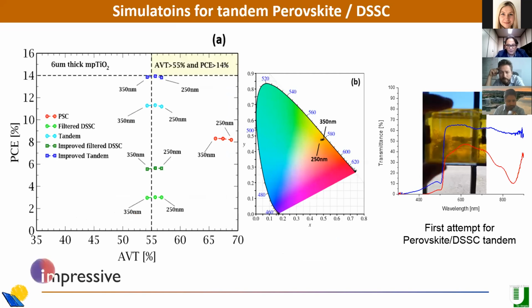At the moment, we have just the first attempt for the organic solar cell perovskite tandem, which is the one on the right. But what the simulation can tell us is what could be the final goal if we optimize all the process and the cell. So if we are able to get a perovskite solar cell with efficiency around 8%, with a transparency between 65 and 70%. So we are not so far from this goal. And if we are able to get an organic solar cell, which has an efficiency around 6% with a transparency of 55%, and at the moment, this is the most critical part of this development. So it is not easy to get to 6% with 55% of transparency.